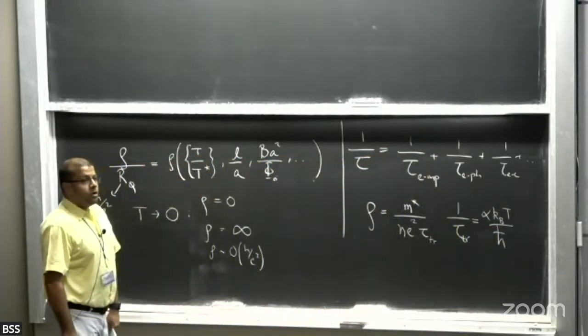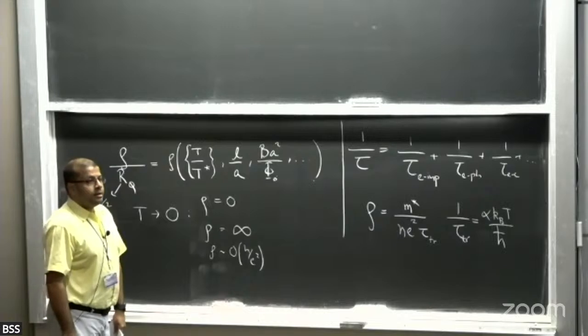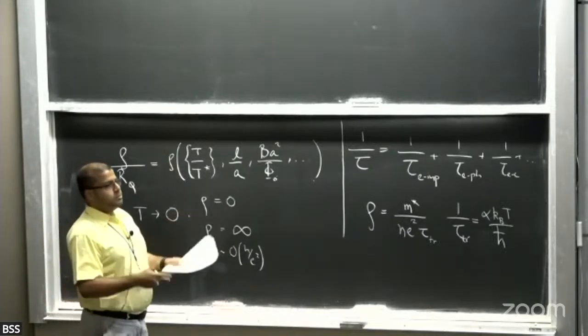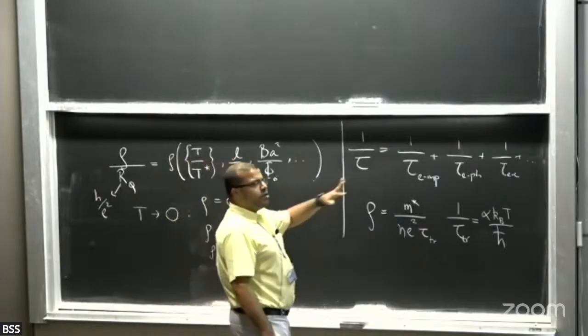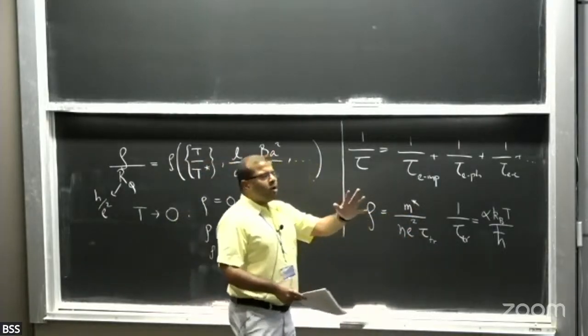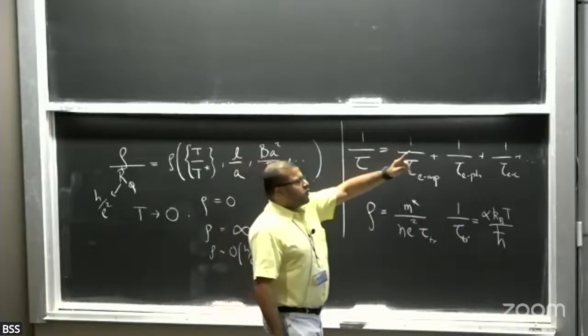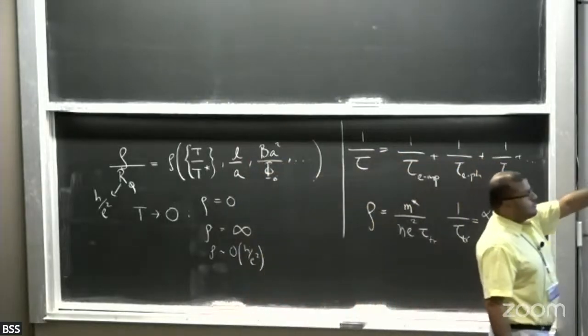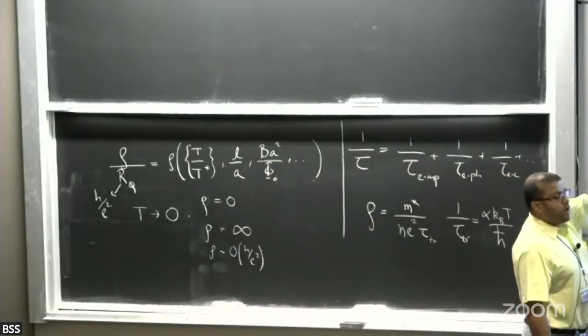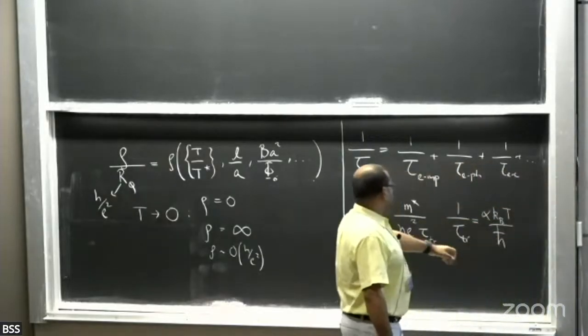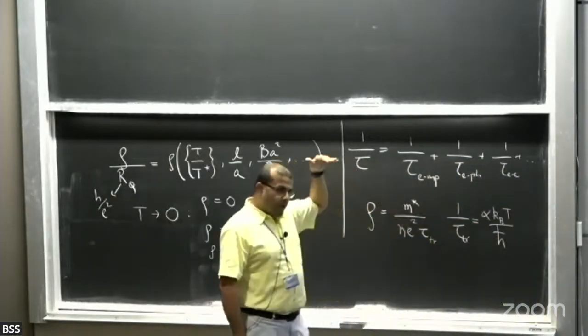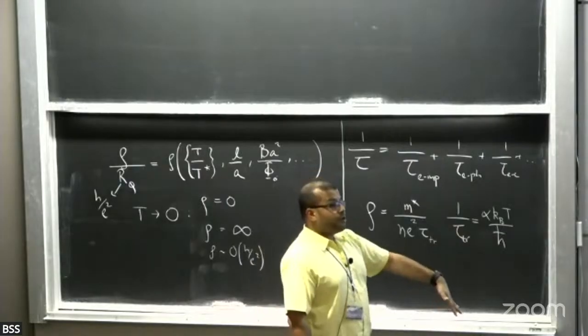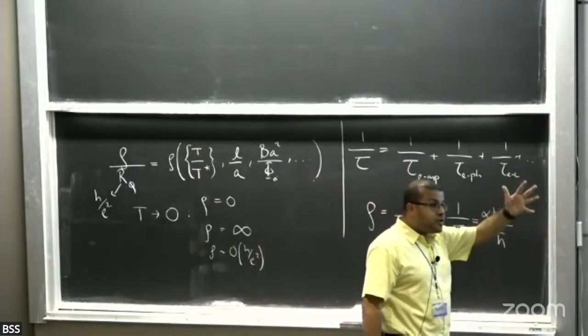And yeah, this is just an assumption. Actually, there are even more assumptions that I talk about in the notes. You're trying to extract a scattering rate from this finite temperature region where you see the T-linear resistivity. You're also trying to extract m star from an asymptotically low temperature measurement. So you're assuming that m star itself is not temperature dependent.